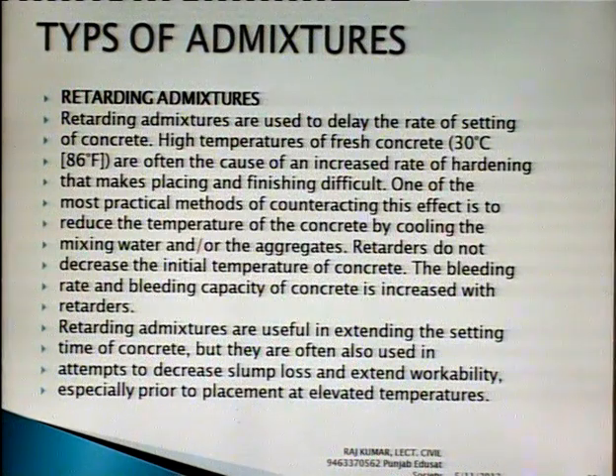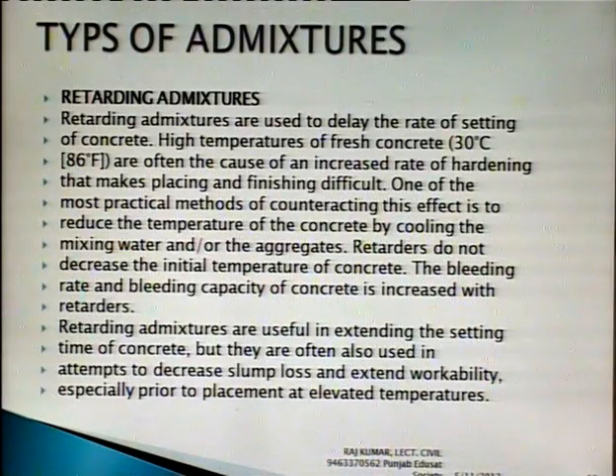cohesive properties. Then retarding admixture is used for delaying the rate of setting of concrete. Higher temperature of fresh concrete, 30 degrees, often causes an increase in the rate of hardening. The mixing and placing and finishing will be difficult. One of the most practical methods of counteracting this effect is to reduce the temperature of the concrete by cooling the mixing water and the aggregates. Retarders do not decrease the initial temperature of the concrete. The bleeding rate and bleeding capacity of concrete increase with the retarder. Retarding admixture is useful for extending the setting time of concrete, but it is often also used in an attempt to decrease slump losses and extend workability, especially during placement at elevated temperature.